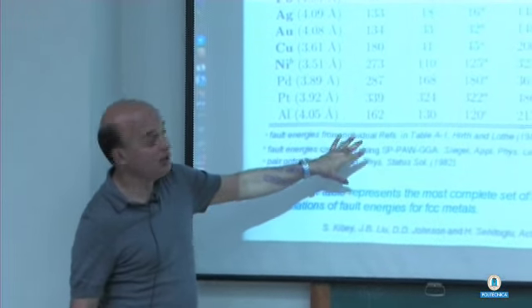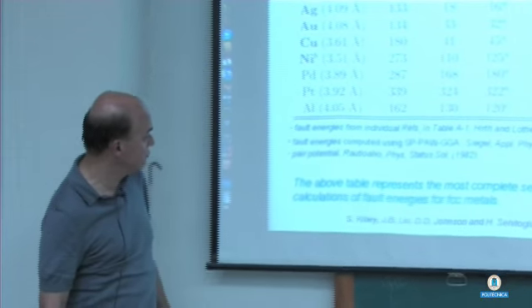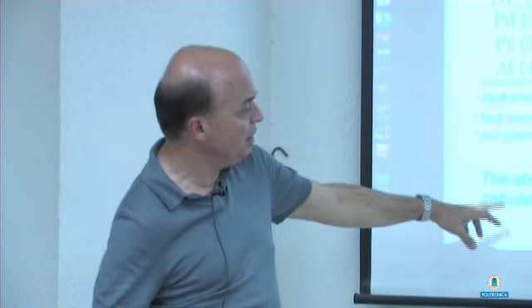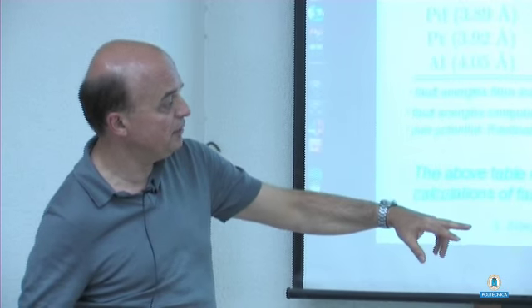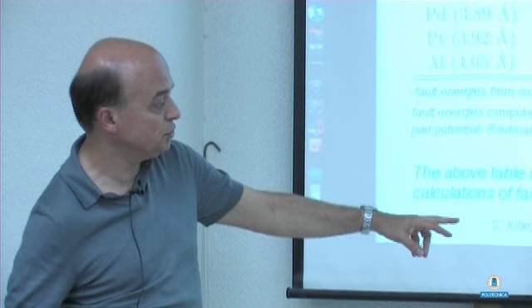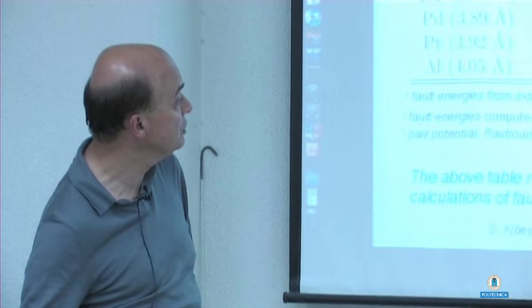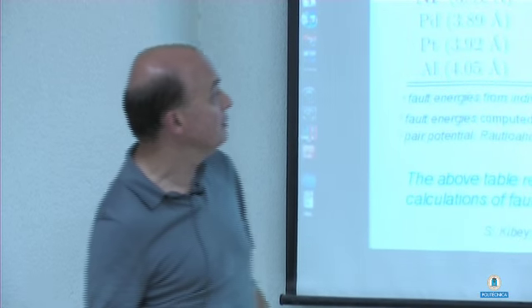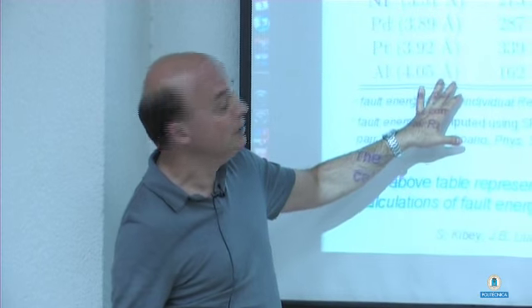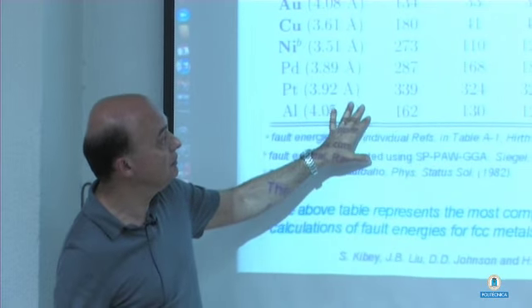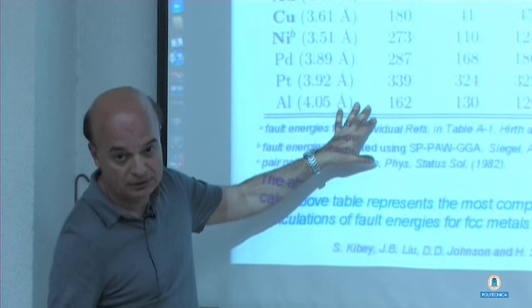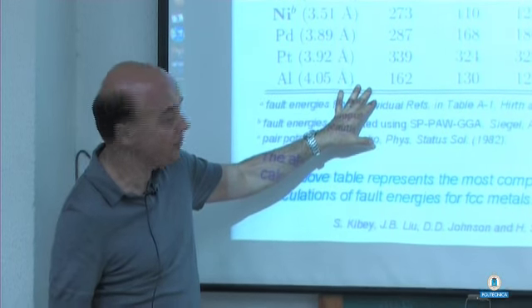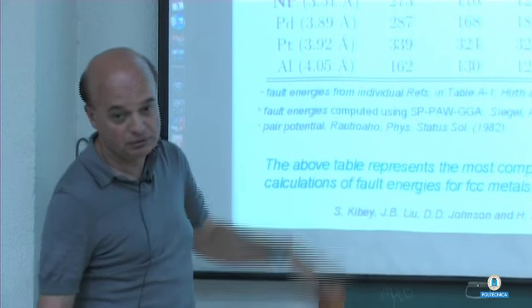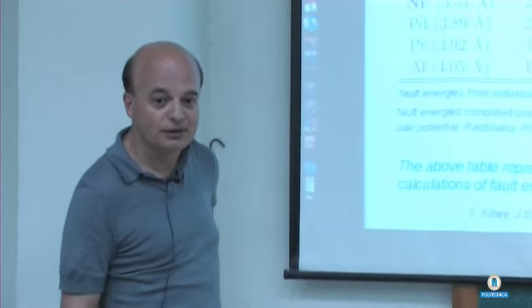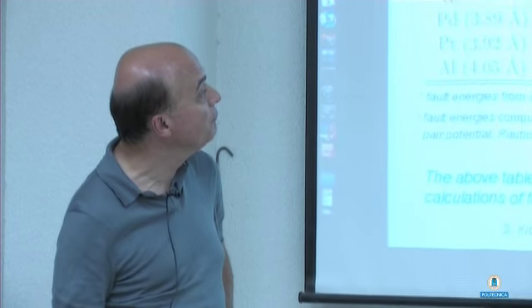Some of these experimental results are taken from the literature. The above table represents the most complete set of DFT-based theoretical calculations of fault energies for FCC metals. Note that there are some metals here that are not known to twin as coarse-grained materials, but we are including almost all pure metals here. Okay. Now,